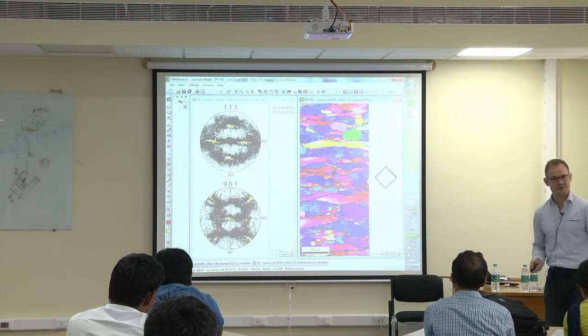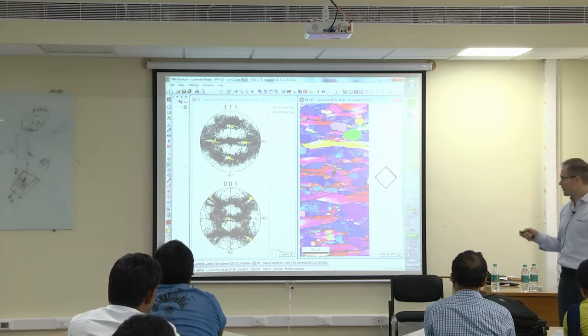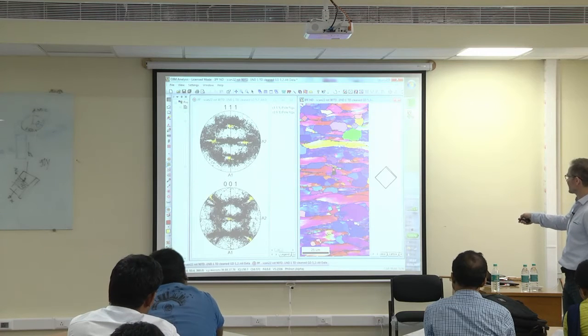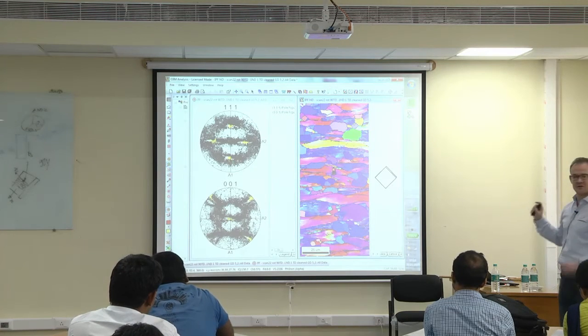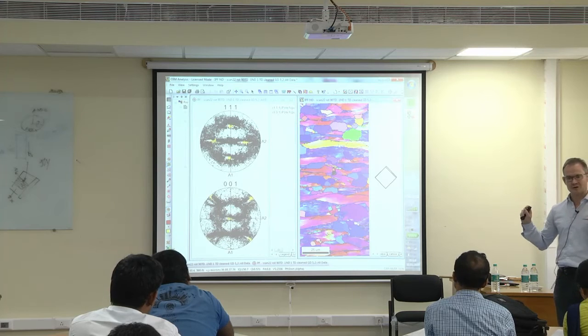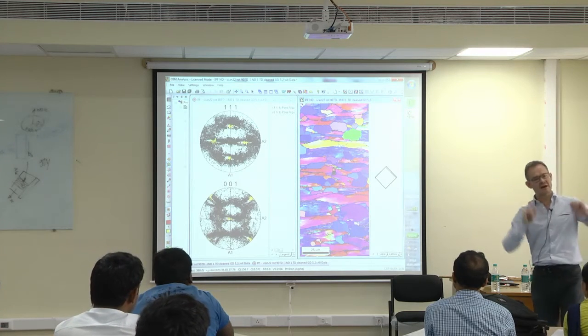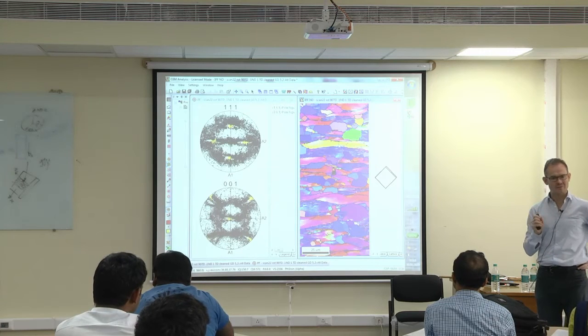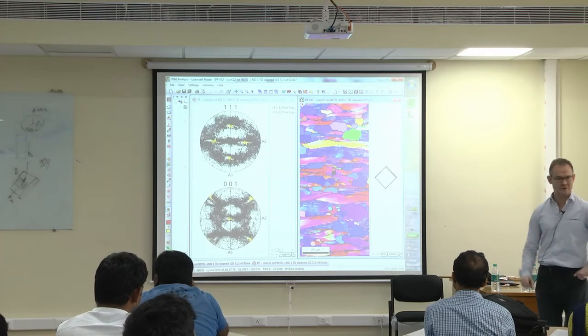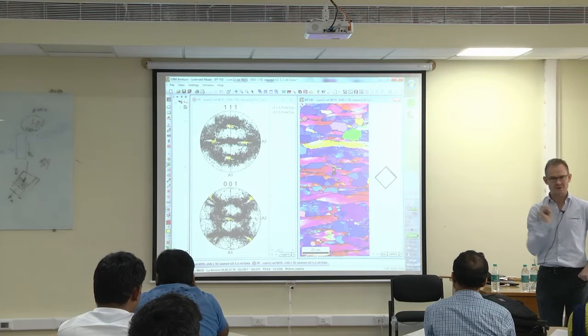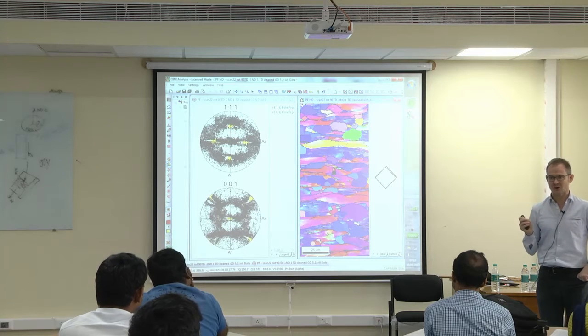Actually, there's 2 sorts of deformed grains, the blue deformed grains and the red deformed grains, and there's more or less one sort of recrystallized grains, and that is only the blue ones. And now you can say, hey, why only the blue ones form out of a texture which consists of blue and red? And that's actually one of the big questions. How do these textures form?